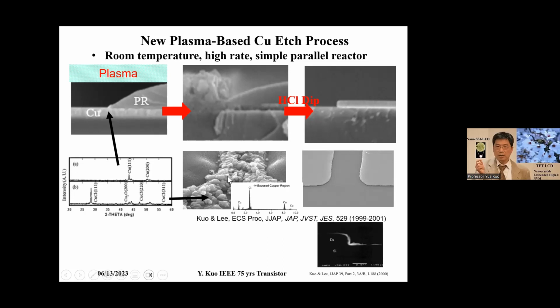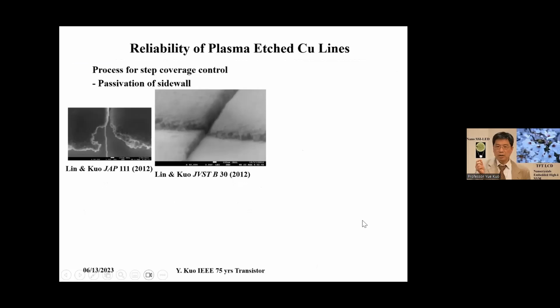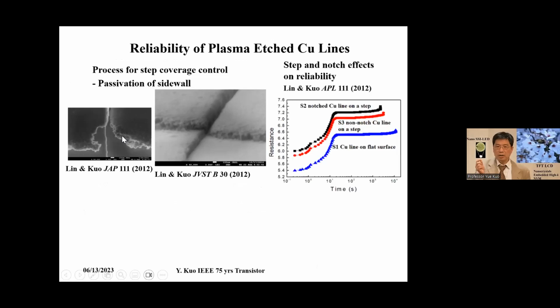Then this layer is dipped in the HCl solution, which has infinite solubility, instantaneous dissolve, then we form a copper pattern. So we reported this in the late 1990s. Then after that, we did a reliability test. We used a method to etch copper on the step. So with proper control of polymer chemistry, we can avoid the cusp formation.